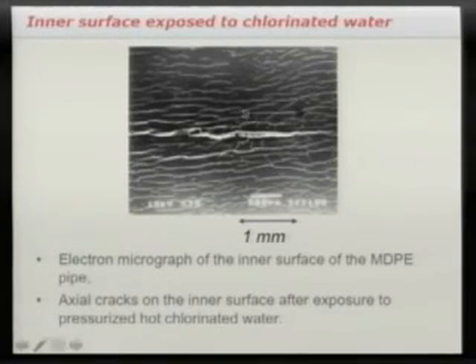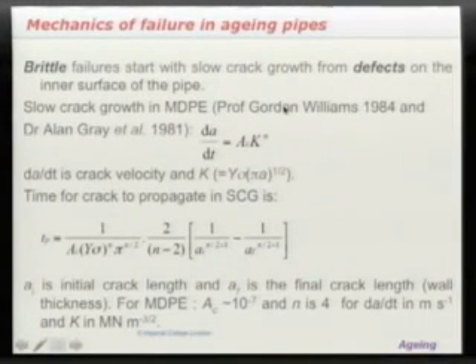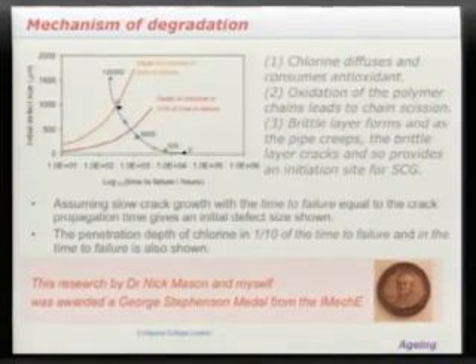When you look at the inside of a pipe surface where water has been flowing through it, after a long period of time, you find this fine network of cracks, which looks a bit like a mud surface which has dried out. And here you can see those little cracks. It turns out that those cracks are determined by crack growth processes, which is promoted by the presence of oxidizing agents. Gordon and Alan developed a model here which determined the lifetime of these components and took into account the presence of those aggressive agents. And we received a medal for that, the George Stephenson Medal from the IMechE.